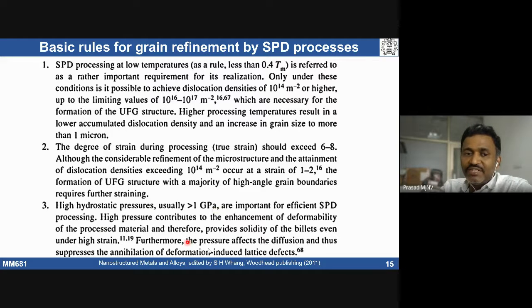This basically maintains solidity. The material will still be in solid form, even under high strain, and we also see reduced diffusional activity. If there is diffusion, then we see easy recovery. We should control the rate of recovery. Then only can we induce a fine grain size in the material and suppress the annihilation of deformation-induced lattice defects. That's the use of a hydrostatic component.